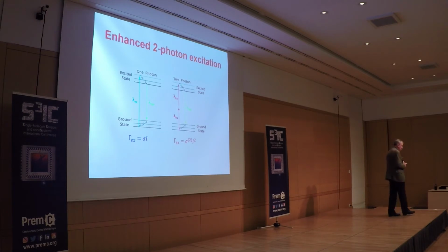And so we thought, in fluorescence, usually we don't enhance the excitation so much because it's usually out of the plasmon resonance, and we essentially enhance the emission. So that's what we did in the previous experiment. But what if we could enhance the excitation twice? Of course, if you go with two-photon excitation, your excitation probability is second order in intensity, so it's already fourth power in field. So you can also have very high enhancement. It can go up to 10 to the 12 or so, not in nanorods, of course, but in small gaps. So what if we could try with gold nanorods to enhance the two-photon process, two-photon excitation, and try to observe that?